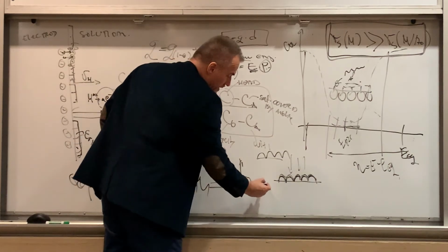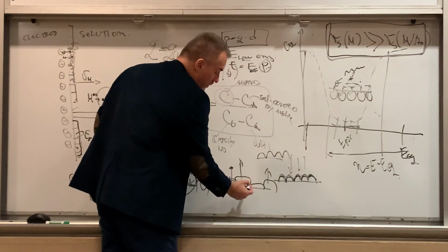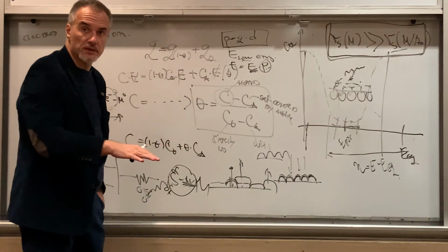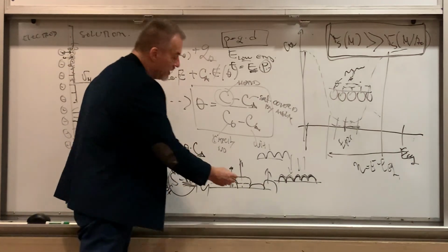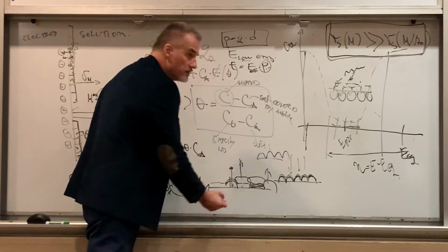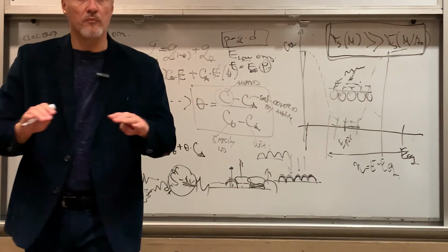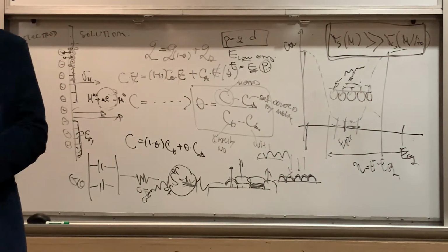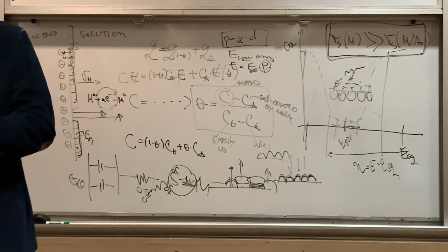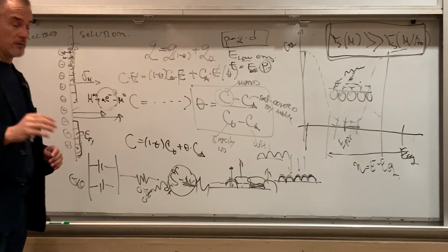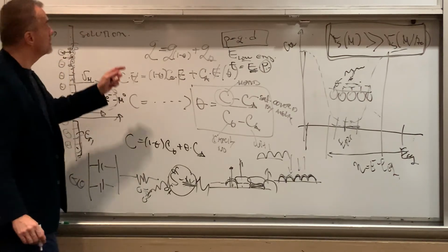And this guy on the other side the same way. And once they overgrow this additive molecule in between, it will be effectively trapped, and we're going to have this covered by the deposit, where this organic molecule will stay in. And that does some specific stuff to the deposit. Makes it either better or worse. We'll discuss that.